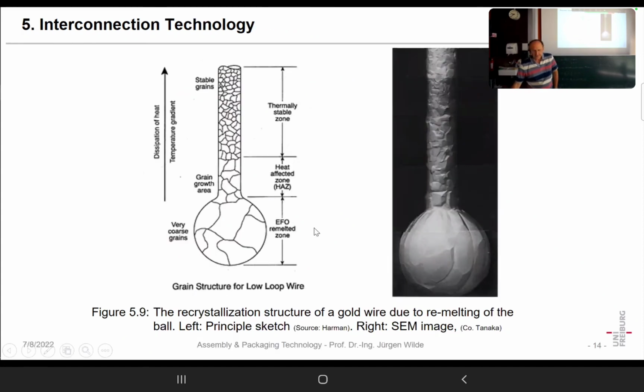And yes, here we can also see such, that also was by Tanaka, a bonding wire, that's internal structure. So we have a large grain structure where the wire was molten. We have the grain structure of the gold in areas where the wire was produced by wire drawing. And also in the neck region here, we have a recrystallization.